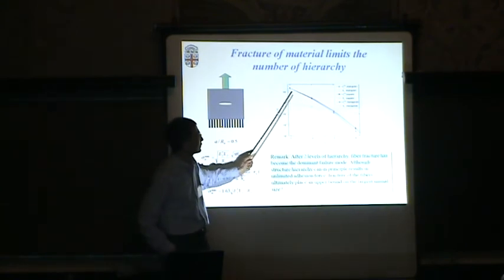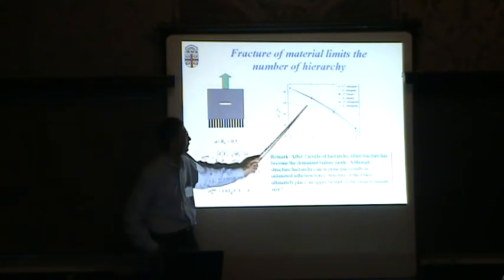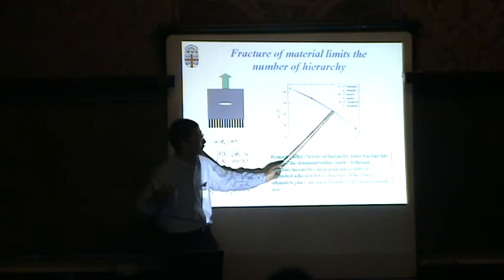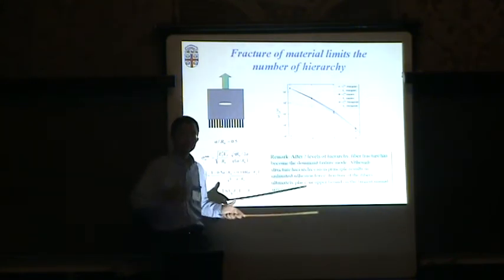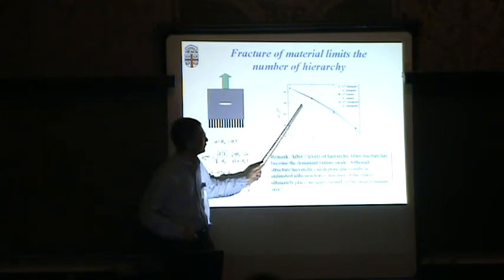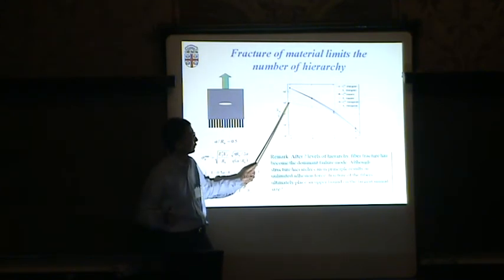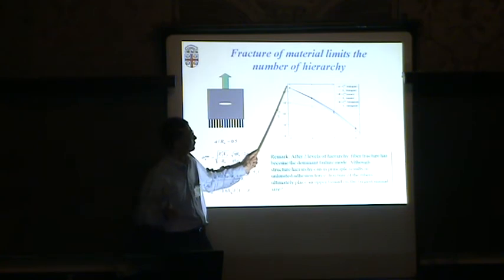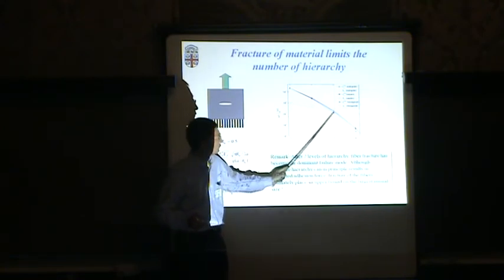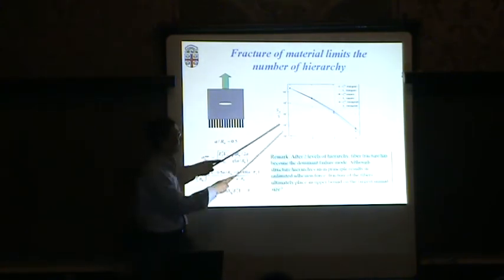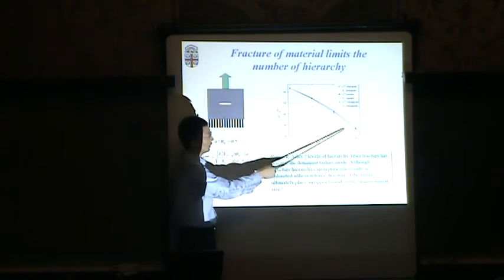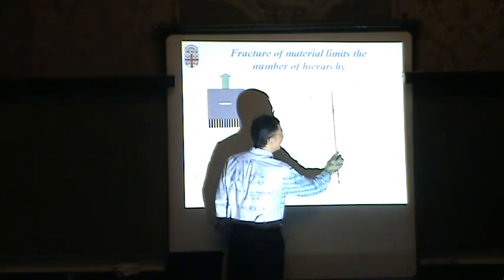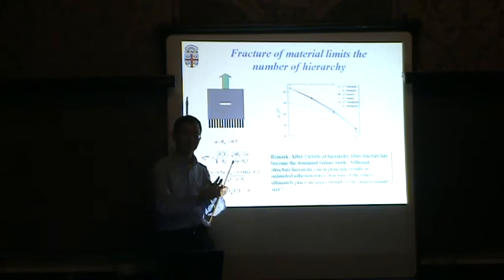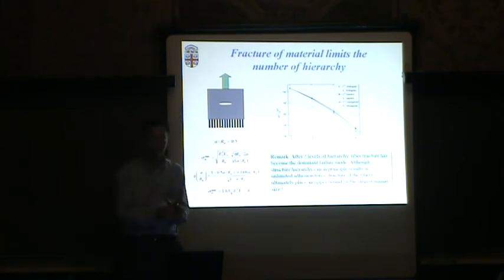So here's the plot. I plot the curves, right? So this is the interface. Okay, this is the adhesion strength of the interface as a function of hierarchy. Okay, as I increase the hierarchy, the material gets larger and larger. Right? So the interface strength decreases slightly. Without hierarchy, interface is the bottleneck. Okay, the material is stronger. The keratin in the material is much stronger than the interface. This is a Van der Waals interaction. That's a covalent interaction. But as I build up a hierarchy, okay, I didn't do anything about the material. So the material strength, you have a crack here, material strength drops. The intersection is here, right? It's about only 2 or 3 level hierarchy. The two curves intersect. That means the failure mode will change. Okay? If you have too many level hierarchy, the failure will change from the interface to the material.